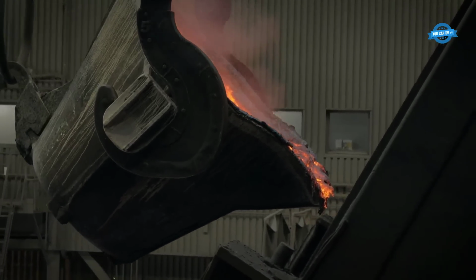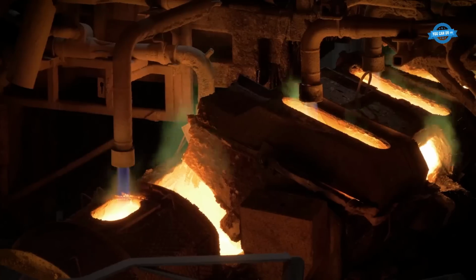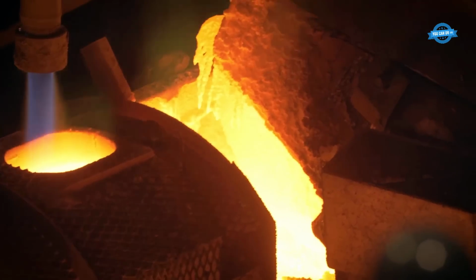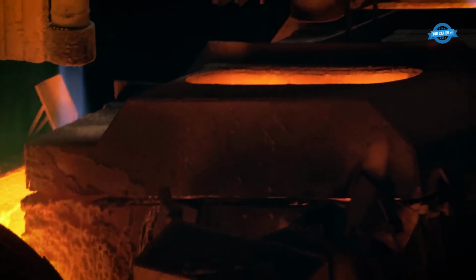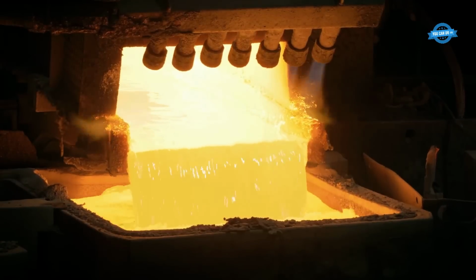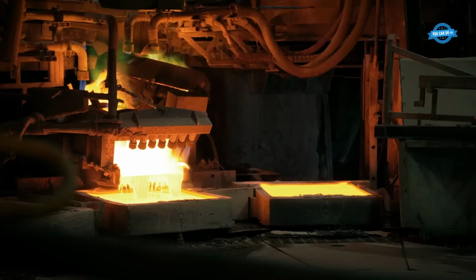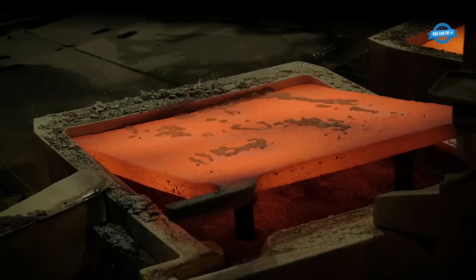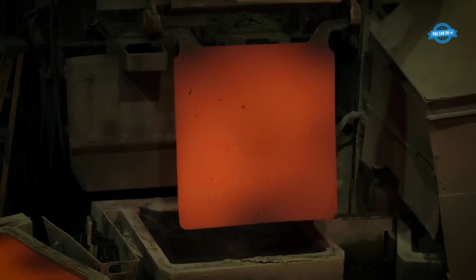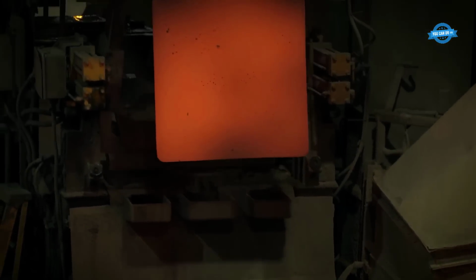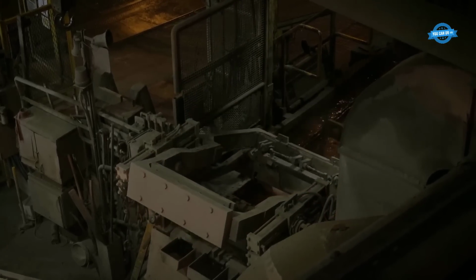Next, materials enter the Noranda reactor. Heated to 1200 degrees Celsius, a high-speed slinger projects materials into the vessel, where they liquefy. Oxygen-enriched air is injected, binding sulfur and iron, forming a gas phase of sulfur dioxide above two liquid layers: slag, containing iron, silica and 4% copper, and matte 70% copper.